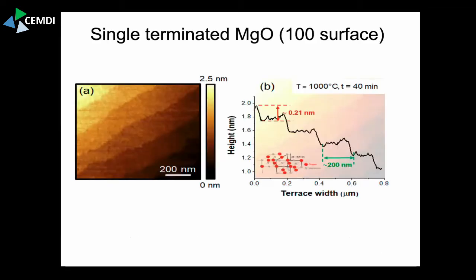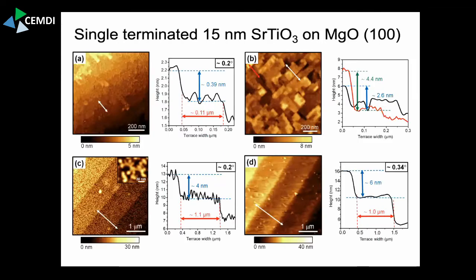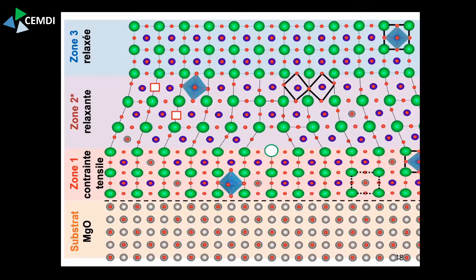And as we grow this, you can think of this as a Lego surface. This is a magnesium oxide substrate. These steps are atomically high, so you see them here. And we grow strontium titanate on top. This strontium titanate has a lot of strain, and it grows beautifully, and it reproduces these steps. So far, so good. So what could possibly go wrong? Well, this could go wrong. I'll leave you a second to let this sink in.